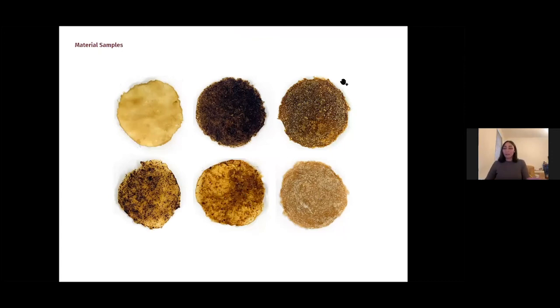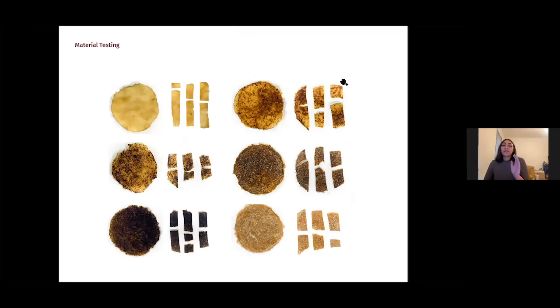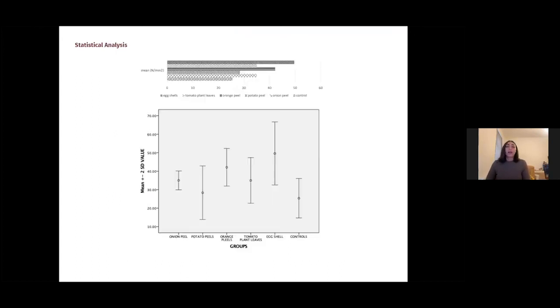And after these samples were made, probes were also made out of them, and they were taken to the universal testing machine, obviously under the same settings that were used to test in the previous phases as well. And here you can see the results. The mean tensile strength of the control group was significantly lower than that of the composite materials, specifically the eggshell group. It's almost double the strength of the control group.